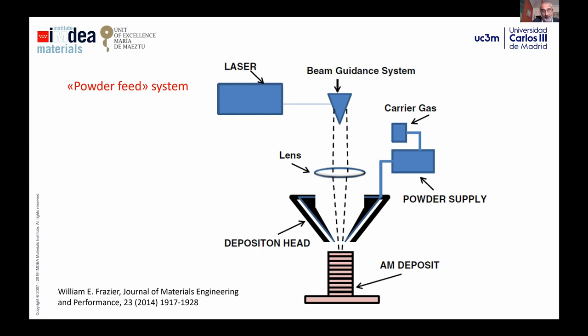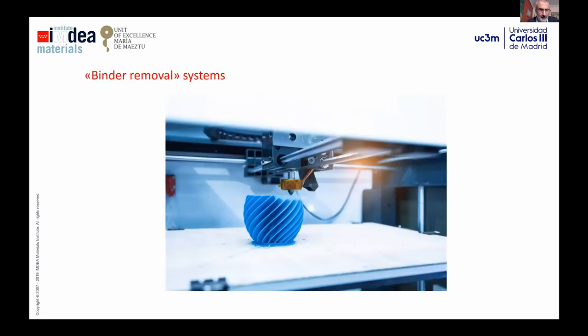And we have a third way to obtain materials by additive manufacturing of metals, which is the so-called binder removal system. In this case, we are printing in a similar way to how we print parts in 3D printing for polymers. But in this case, we need a feedstock, a mix of polymer and metals, in order to have a good printing method. Once we have the printed part, we need to remove the binder. Sometimes the amount of binder is not so high, like for instance in the HP method, in which we have a very small amount of binder, but there are other methods in which the amount of binder is much higher. Once we have removed the binder, we have to move the part to a sintering furnace to reach the final properties after a conventional sintering process.